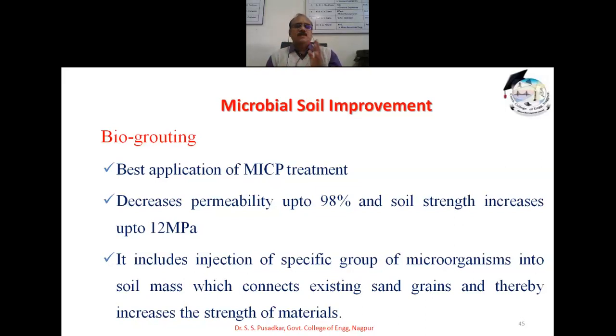So biogrouting decreases permeability up to 98%, and definitely when it's sealing the cracks, it will be binding the particles, so it will increase the strength up to 12 MPa for that particular type of sand which has been tested. It includes injection of a specific group of microorganisms into the soil mass which connects the existing sand grains and therefore increases the strength of the materials.